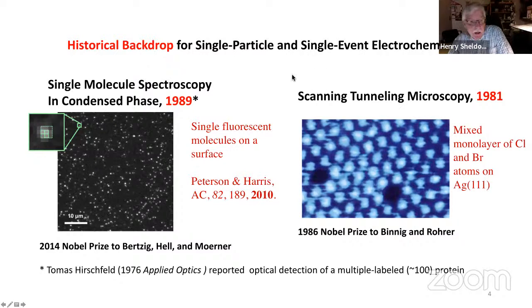So what happened? In 1995, we saw this explosion, and I think the reason for that, at least partly, is that shortly before that we had the development of STM in the early 1980s. This is an STM image of halogen atoms sitting on a silver 111 electrode from my lab. This is the ultimate single particle electrochemistry experiment because you can see single atoms and you can see single molecules. You can do this all in situ. And very shortly after STM was invented, by 1990, not every electrochemist, but a very significant fraction of the electrochemical labs, had an STM, because this is the way you could really see surfaces under or in an electrolyte phase. And then 10 years later, the first single molecule spectroscopy experiments appeared.